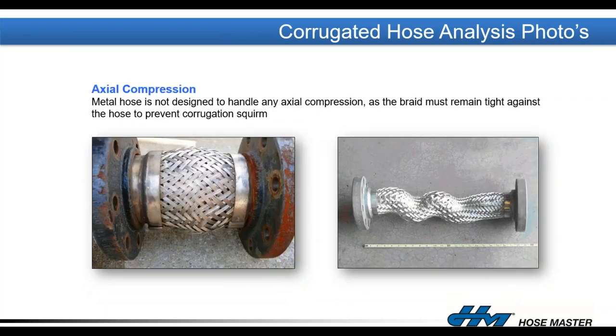The picture on the left on the next slide is a short pump connector, and this is something we see all the time where customers use inexpensive braided flex connectors. That hose isn't even long enough to handle any movements, much less any vibration from that pump. It'll fatigue and fail very quickly. You can see the braid has relaxed away from the hose because invariably these get compressed over time. And if it's a longer assembly, allowing that braid to slack away from the hose, you'll see what's pictured on the right-hand side where the corrugations actually deform and squirm underneath that braid. So avoid compressing that hose assembly at all costs.